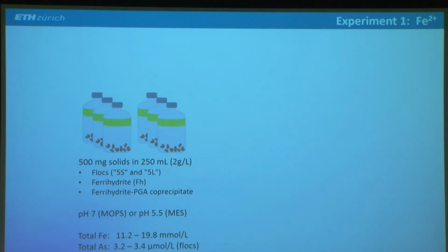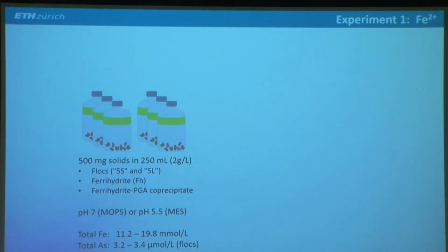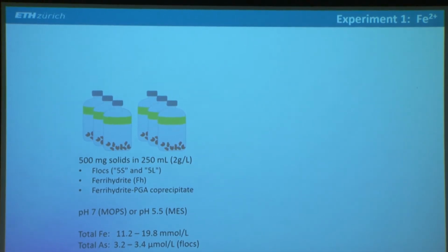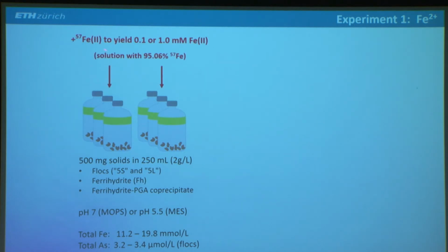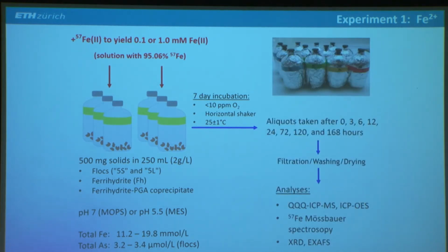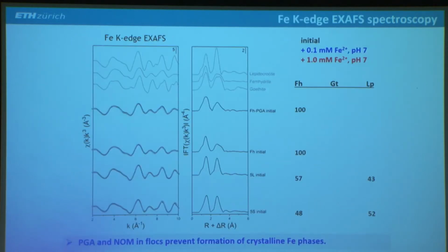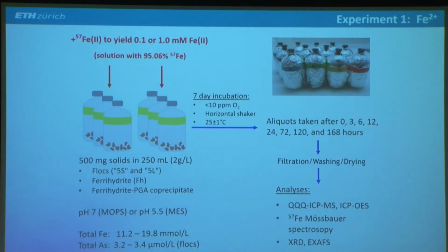So the way the experiment was done is we took these septum bottles with 2 grams per liter of flock material. We also did the experiments with pure ferrihydride and also with a ferrihydride polygalacturonic acid coprecipitate. That's kind of a synthetic iron organic coprecipitate. Then we spiked iron 57 with 2 different iron 2 concentrations. These are the final concentrations in the system. We incubated these samples for 7 days in an anoxic glove box. We then took some aliquots after different time intervals, prepared them for analyses, and used different techniques to analyze the solution and the solid phases.